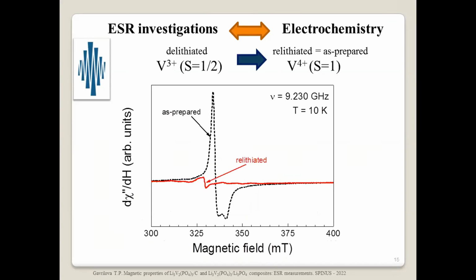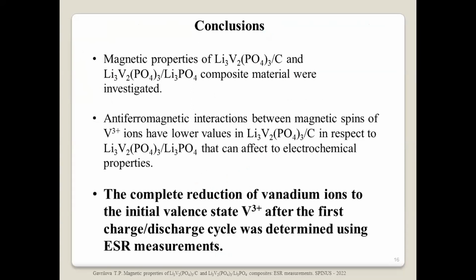And what we observe is that the signal from the relithiated sample is much lower than the intensity of the signal from the as-prepared sample. It means that all vanadium ions go to their initial state, vanadium 3+, and it is very important from an electrochemical point of view. It means that we can use this compound as a potential cathode material for lithium-ion batteries.